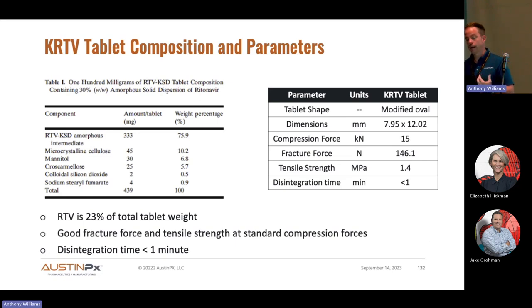Ritonavir is sensitive to acid catalyzed hydrolysis, but the cycle times of KinetiSol being so short, it prevents degradation due to HPMCAS exposure just by virtue of the short processing time. And then we were able to incorporate 75% of that dispersion in the tablet. So we fit a 100 milligram dose into a tablet that weighs less than 450 milligram.